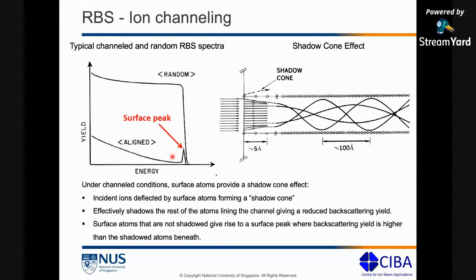And then you have this characteristic feature that you will always see for a channel spectrum. It's called a surface peak. What that means is, if we are able to visualize the atomic rows of a single crystal silicon from a horizontal perspective, from the side, we have the top row of atoms and the bottom row of atoms. And let's say we have aligned this atomic row to the incident ion beam. So we have these alpha particles coming in here. Because the channel is aligned to the incident beam, most of these ions are going to go straight in, and they're going to have this spiral path as they enter the channel. And that's what is going to give you a drop in the backscattered yield, because all of them are going in now, nothing is backscattering, right?